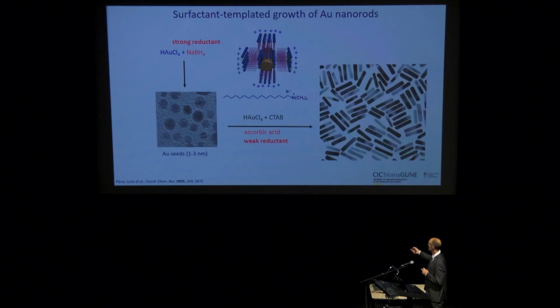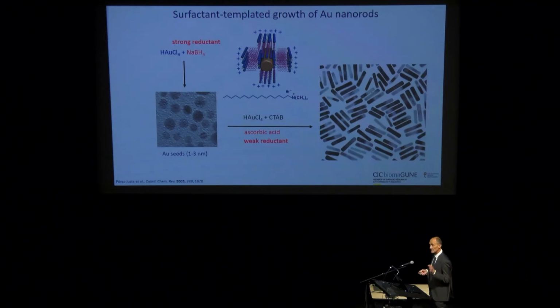So since these particles are to be stabilized in water, we typically add enough surfactant that there is formation of something that probably looks like a bilayer, so that you have also charged head groups on the outside, and you obtain an electric double layer that will stabilize the particles in water. So this is quite important. It will be relevant to most of my synthesis part.